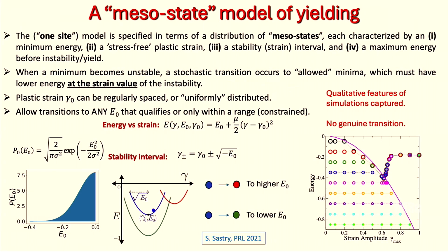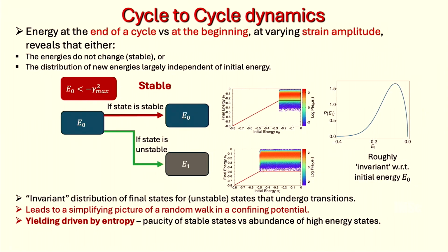So these are qualitative features of yielding that are reproduced, except that for this particular model, this is actually the behavior of the system after a certain number of cycles. There is no genuine transition, because if you wait long enough, eventually you'll find the minimum which is deep enough and stable enough that you don't then make further transitions out of it. So this reproduction of simulation results is a little bit misleading, but one can build on this as I described and try to do better.